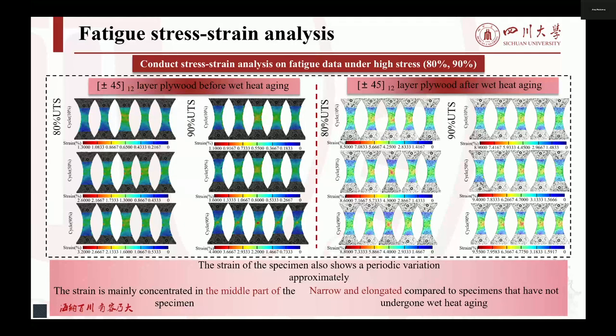The DIC technology was exploited for analyzing the full-field strain distribution and evolution. For the DIC image of the 45-degree laminated plate, it is evident that the strain of the specimen exhibits an approximately periodic cycle, which is related to the fatigue stress loading. The damage propagates from the interior towards the 45-degree direction, determined by the fiber angle. The test piece after hygrothermal aging will be elongated more, because hygrothermal aging makes the fiber more ductile.